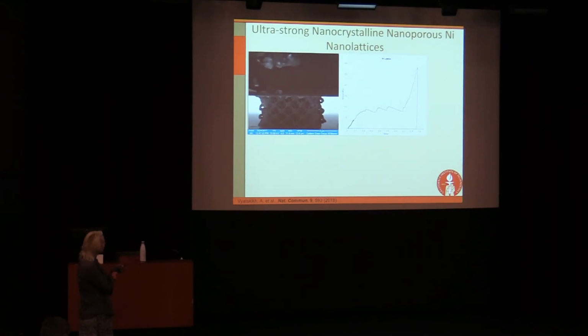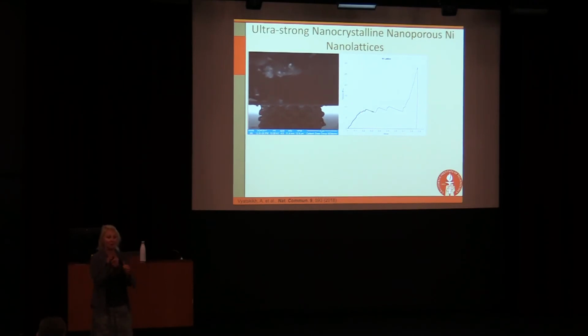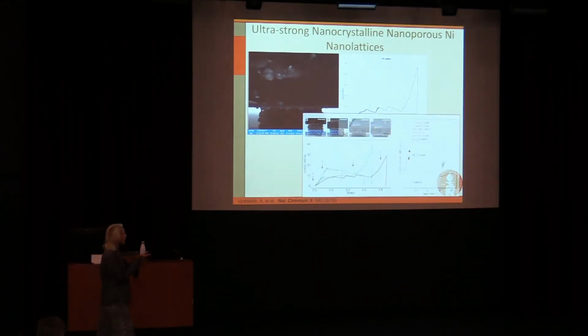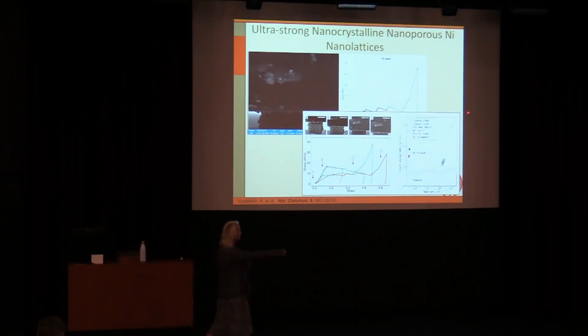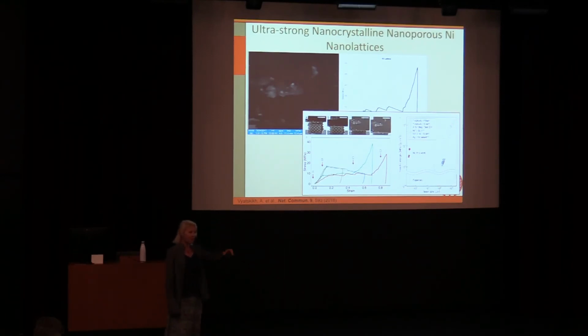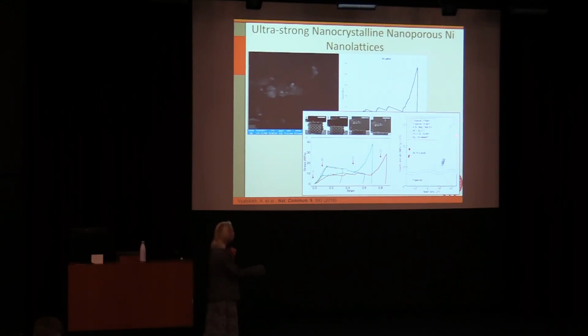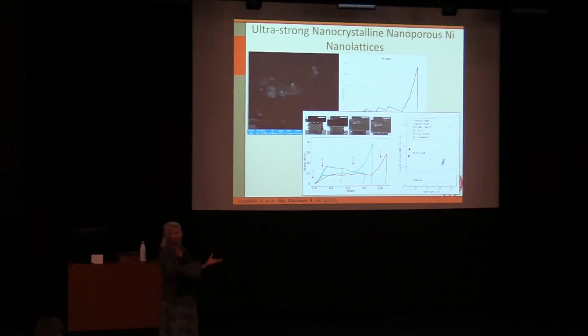So here's some legitimate mechanical data to show you it is in fact nickel. It should be really crappy nickel. It's very nanocrystalline, very nanoporous, not entirely pure, but look how much better it does than everything else today. This is the specific strength as a function of beam size. And this is what everybody can do. What that shows is actually quite eye-opening. This is all the additive manufacturing processes available today, and it shows you a tremendous rate at which the strength drops as you try to reduce the dimensions. When you go from 1 millimeter to 100 microns, you lose 2 orders of magnitude in strength because the other additive manufacturing processes all suffer from defects, and the defects are detrimental.